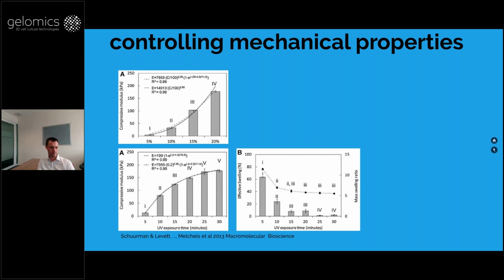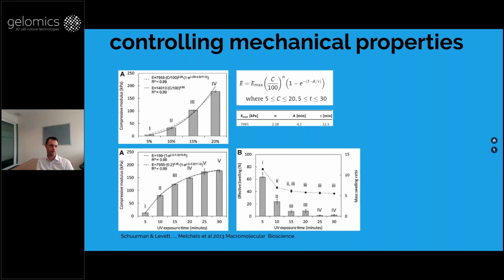But we had standardized these conditions in Brisbane, also in Utrecht and Würzburg, and in Christchurch, and the different groups that collaborated all worked on GelMA, so we could compare the results. And we found that we could really pinpoint the stiffness really well. Here you see the mathematical formula, and the dashed lines represent how the stiffness develops with exposure time and at each concentration. So it's important, but for natural materials, it's quite tricky, usually, to tailor this. So we were quite happy that with GelMA, we could really control and reproduce the stiffness as well.